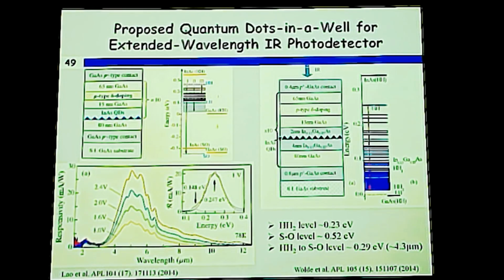Now what we can do from here is look at the difference between heavy hole 2 and the SO band. The SO band is not shown in this figure, but it will be there. If we look at this difference, heavy hole 2 to SO band, the energy difference is 0.29 electron volt, which corresponds to 4.3 micron wavelength. If we get a peak at 4.3, this is the kind of typical detector we are looking for, 3 to 5 micron detection. This device operated at 78 Kelvin, or so, liquid nitrogen temperature.